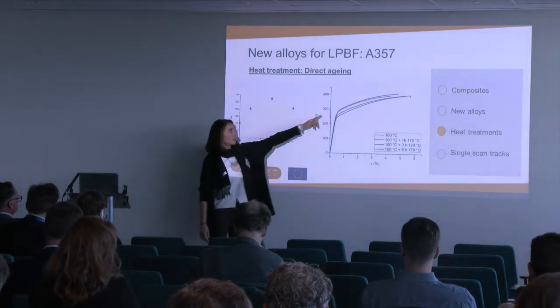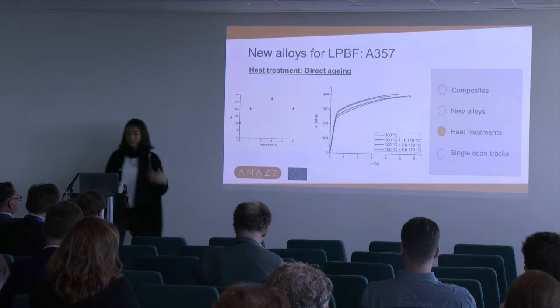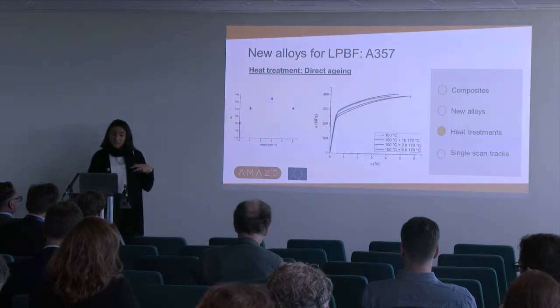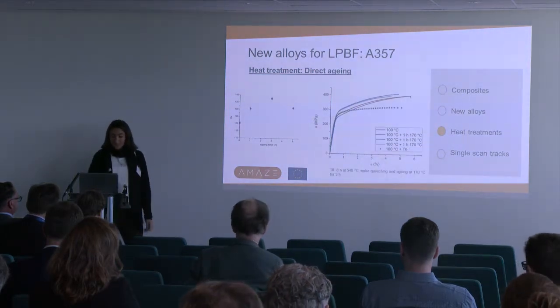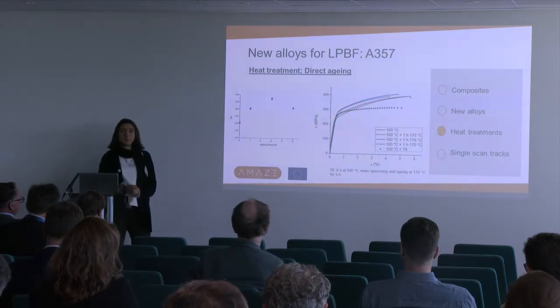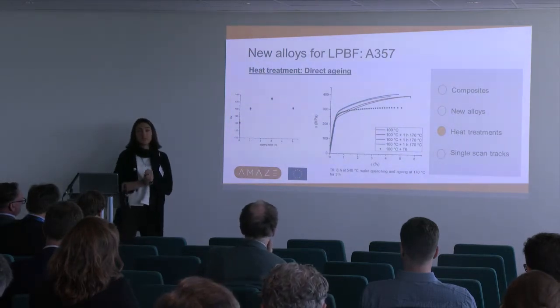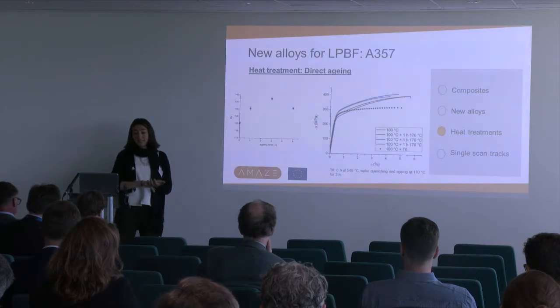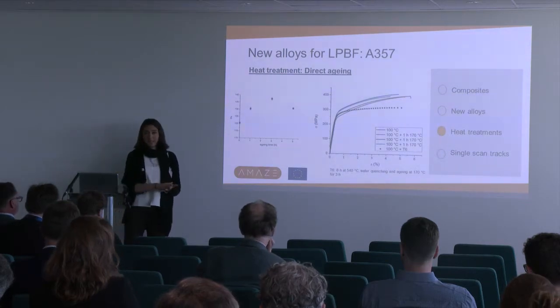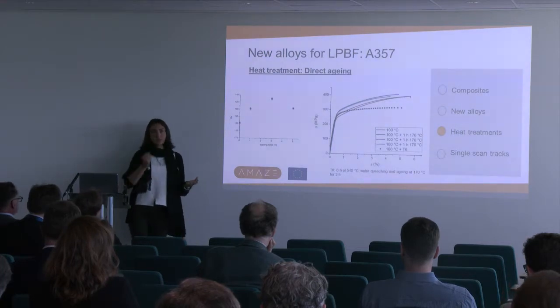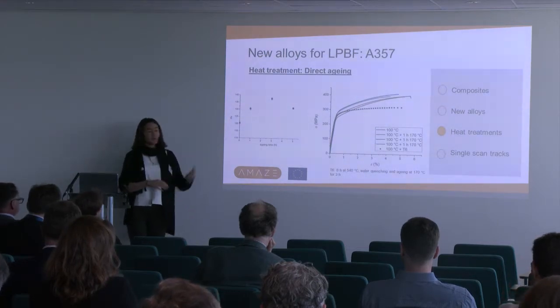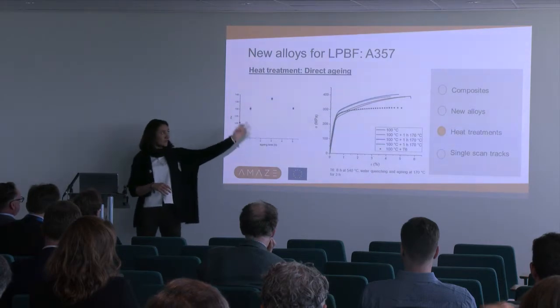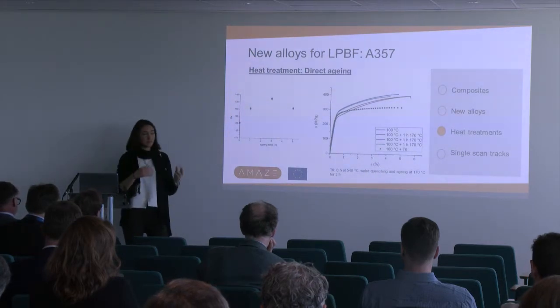So the blue and the green curves are the aged ones. So if we compare these mechanical properties with the mechanical properties of an A357 sample built by powder bed AM, but with the classical T6 heat treatment, so solution, quenching, and aging, we can see that our direct aging can achieve higher mechanical properties.